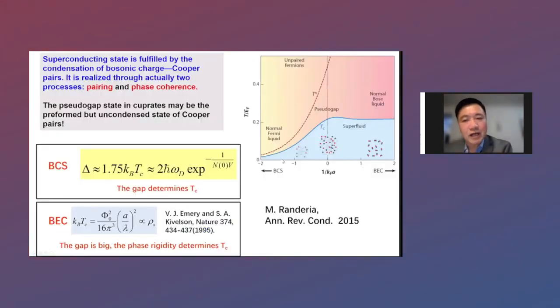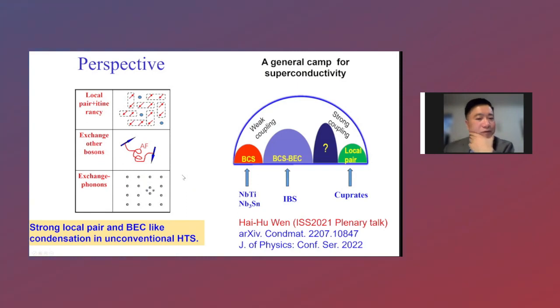And also this kind of cartoon picture says that in the cuprates, we probably have a local strong pairing with a BEC, and when the Cooper pair density becomes higher and higher, we are crossing over to the BCS region. So in that case, I plot this kind of cartoon picture. In the BCS case, we have the Fermi surface instability due to weak coupling, like phonon exchange. And in the cuprates, probably, as I showed by 3 pieces of experiment, we have a local strong pair due to the correlation, and also the Tc is determined by the phase coherence, okay?